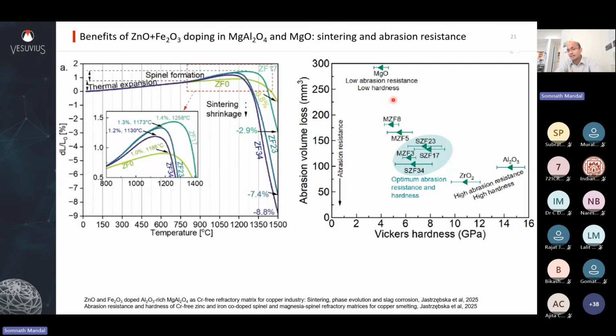So if you have a basic matrix, a magnesia rich matrix with zinc and iron doping, your abrasion resistance is increasing and your hardness is increasing. You don't get to the level of alumina, zirconia, the wear resistant ceramics, but you are improving from the starting point of magnesia, and that is beneficial because you have a more wear resistant, erosion resistant matrix.